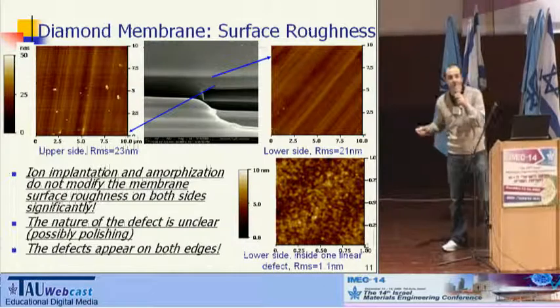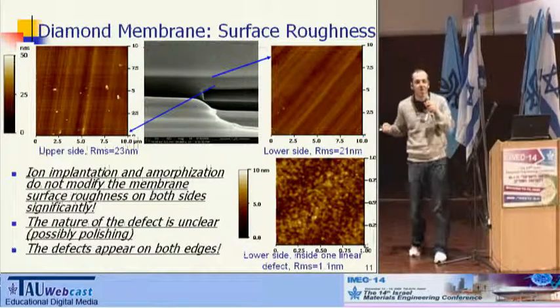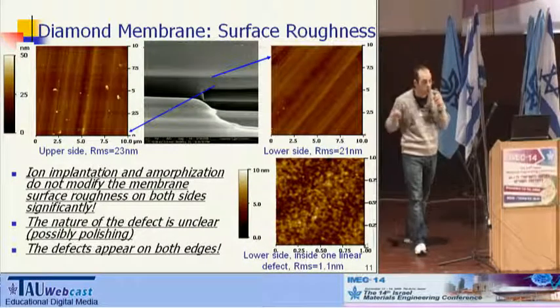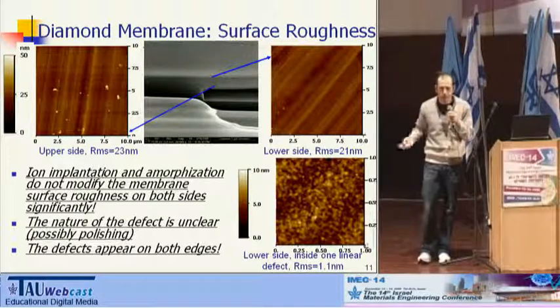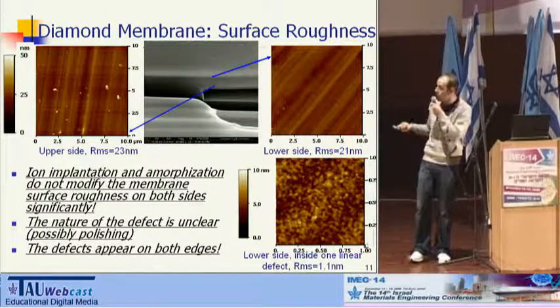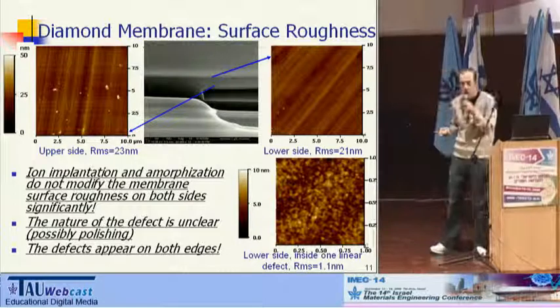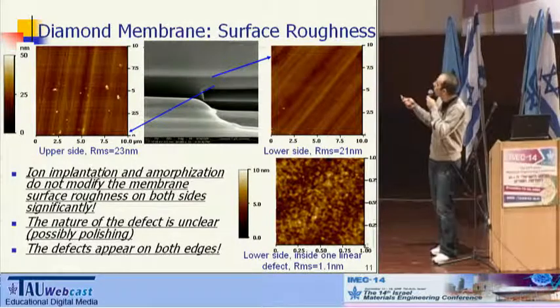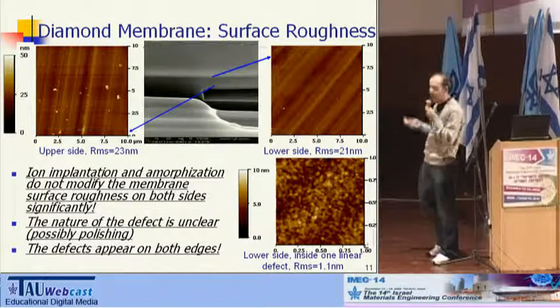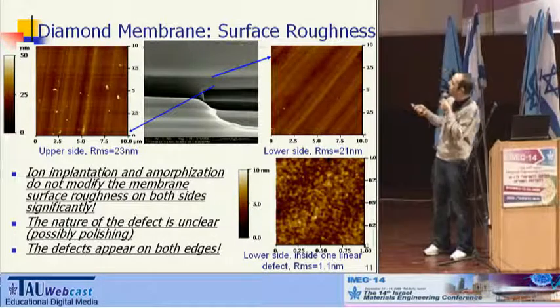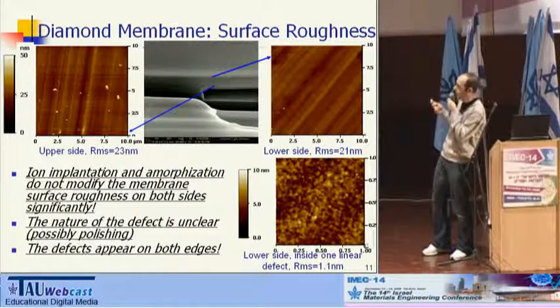Now, when we first have this single crystal diamond membrane, the first thing we would like to do is to characterize its defects. And the first thing we've done is the characterization of surface roughness. We have characterized both the upper and the lower side of the membrane. And here you can see the AFM, which is a square of 10 by 10 microns.